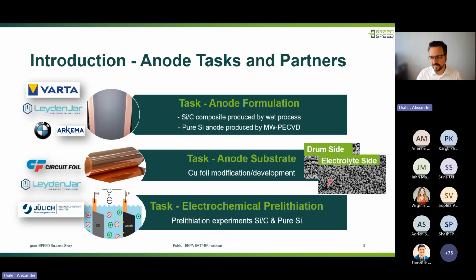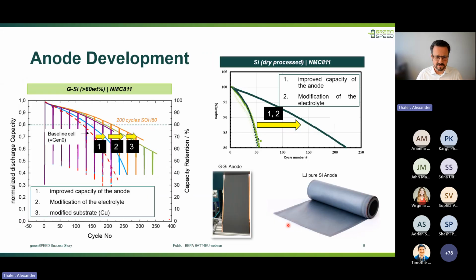They deal with the modification of the anode substrate, so that these high silicon anodes can be attached to it quite well on the adhesion side, but also improving the lifetime. And to get all these high energy dense materials to work, there is one big part dealing with pre-lithiation, which is Forschungszentrum Jülich, actually on both of our anode solutions.